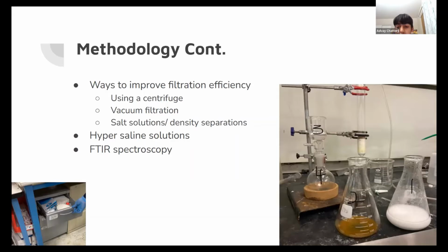There is no universal method to quantify microplastics out of the digestions. The microplastics are quantified visually by counting each microplastic individually with a dissecting microscope and ultraviolet light. These microplastics are analyzed and identified using FTIR spectroscopy by comparing the FTIR baselines for common plastics to those in the microplastic samples from the digested mussels. The findings obtained from the research will be utilized to compare the amount of microplastics filtered and retained by mussels of different sizes with regard to their varying exposure to microplastics.